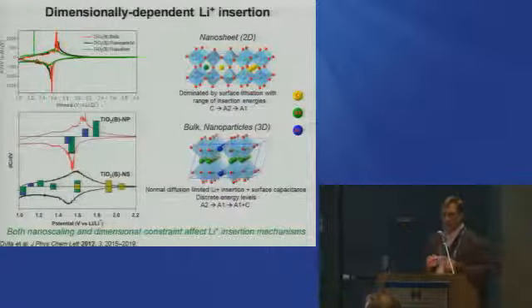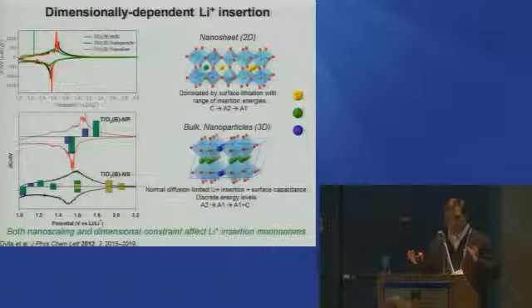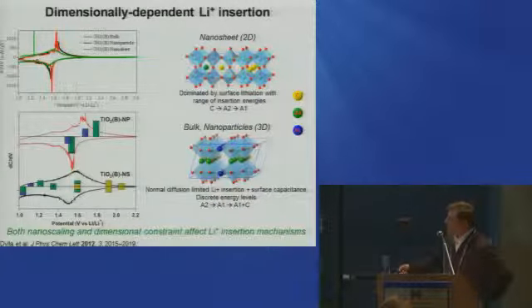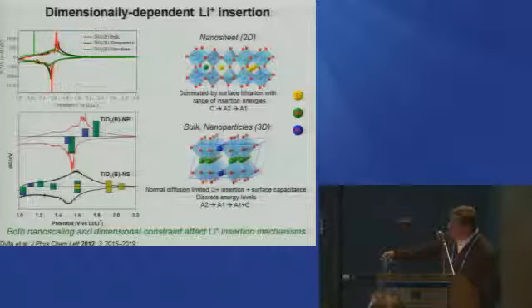And this explains both the shape of these typical cyclic voltammograms, if you want to call them that, and the reversibility. And the hysteresis in the lithium insertion and deinsertion is related to coulombic interactions within the number of sites that can be lithiated. And so the theory actually bears this out.